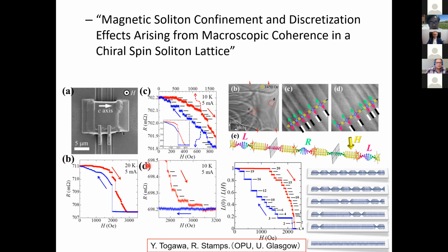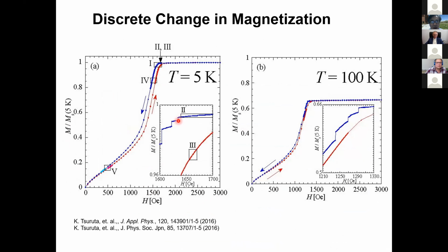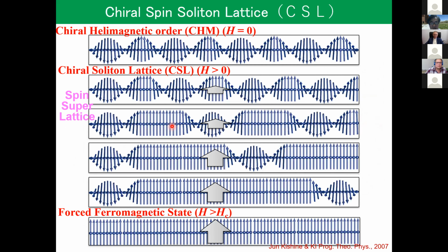This case, yes, this is just a cartoon view. And you also find a step in the magnetization. This is the field dependence of magnetization. As you can see, there is a step, and this step corresponds to one soliton. But anyway, this system is topologically protected, and there is no influence by any defect, and we can change smoothly this helical magnetic order to ferromagnetic spin order.